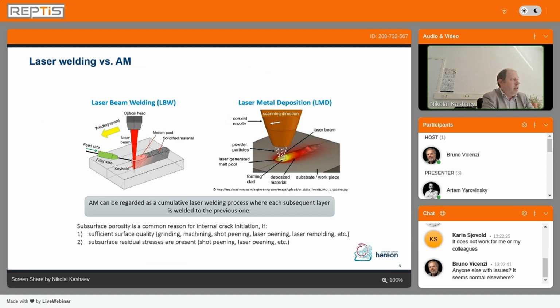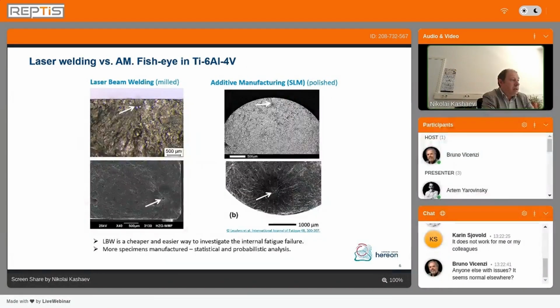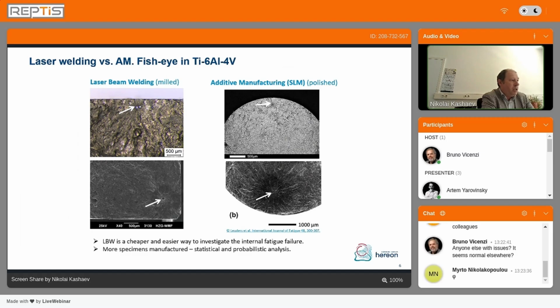And as laser beam welding is the most efficient technology to produce specimens with relevant microstructures for investigating the fatigue behavior, our study was focusing on the laser beam welded component at first. And then we are interested in how we can transfer the results to additively manufactured structures. And here there are examples. For example, if we consider the fatigue behavior of laser welded or additively manufactured components, also using laser beam, we see that we have similar behavior. If we have internal crack initiation from internal porosity, we have the so-called fish eye failure, and it is present in both cases, in laser beam welded joints or in additively manufactured structures.